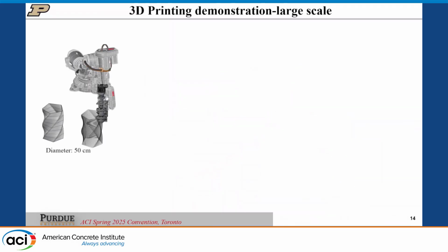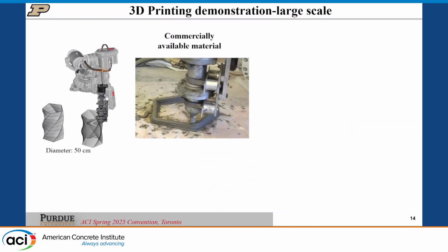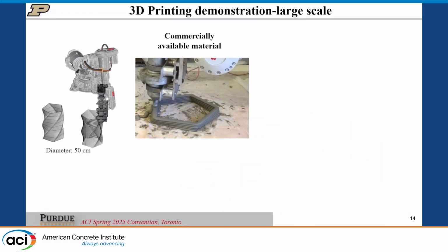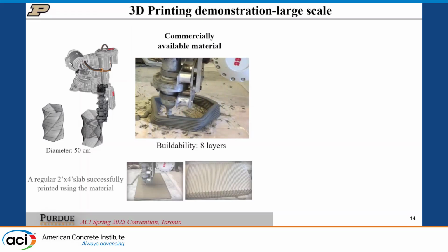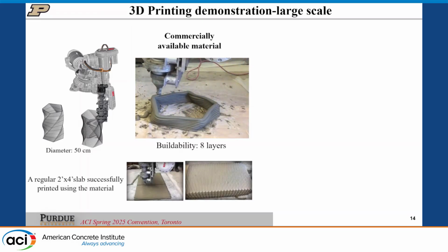So we wanted to take this and do a large-scale evaluation and compare it to what's out there in industry. We obtained some commercial material and again tried a challenging rotating structure, and here you can see around 8 layers we started to have some buckling issues in the system. Again, there's nothing wrong with this system, we're just trying to challenge the printing geometries and see the limits of the rheology.